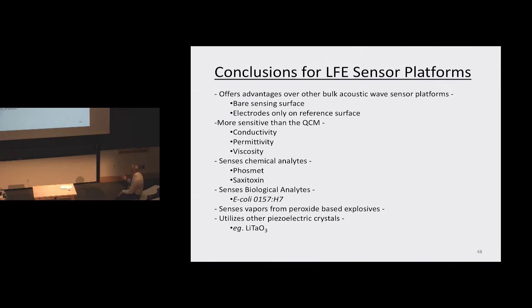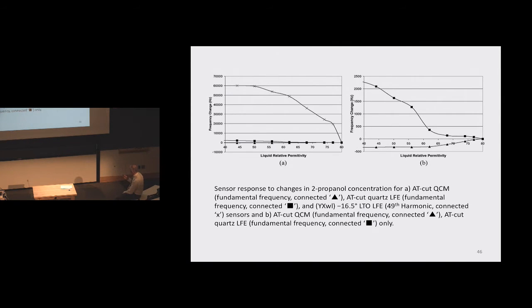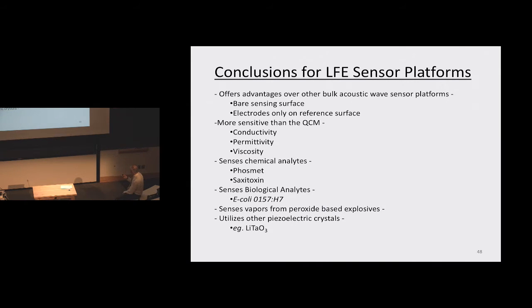So conclusions for the LFE sensing platform: it offers advantages over the other bulk acoustic wave platforms, and in particular highlighted in terms of the so-called bare sensing surface. Electrodes are only on the reference surface. This enables us to detect electrical properties, which cannot be done with the QCM. It's more sensitive than the QCM in all three cases. These two understood. This one a little surprising. Senses chemical analytes, Phosmet, saxitoxin, biological entities, sensing vapors from peroxide-based explosives, and we can use other piezoelectric crystals.